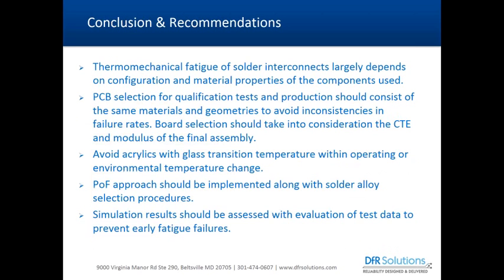To briefly summarize: thermomechanical fatigue largely depends on your component configuration and material properties, which dictate the loading condition and failure mechanism in solder joints. PCB selection and glass style are critical to your final CTE and modulus properties, which will dictate solder fatigue life. Whenever selecting a PCB, you must ensure your final CTE and modulus are optimal for your desired fatigue life performance from a solder joint reliability perspective.